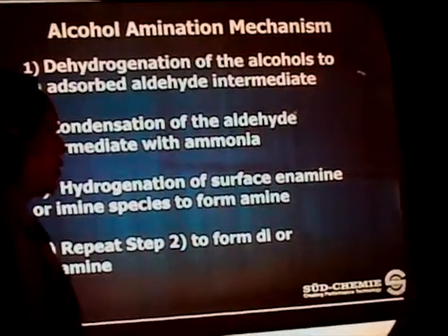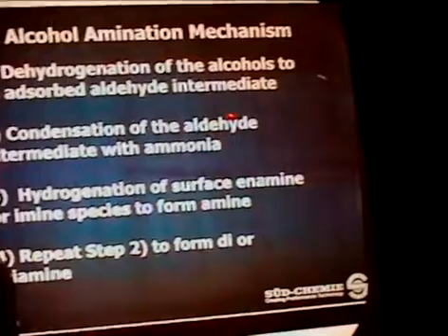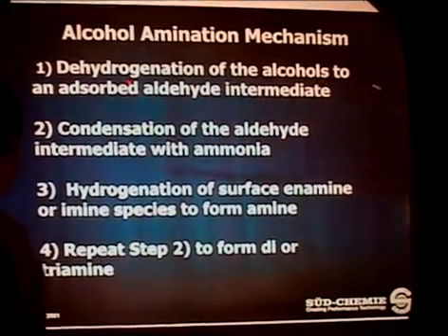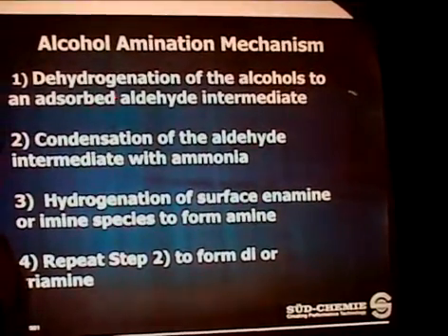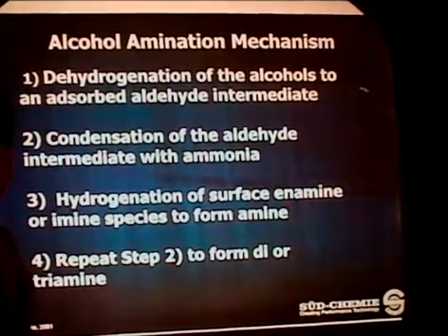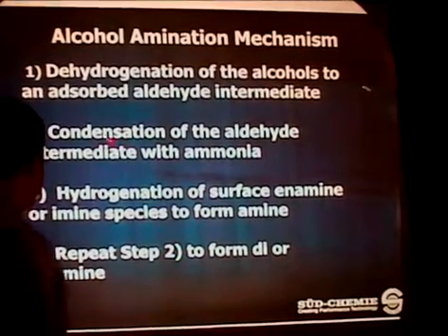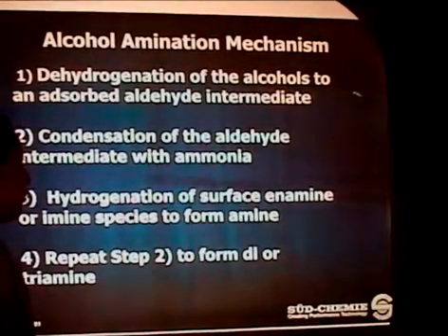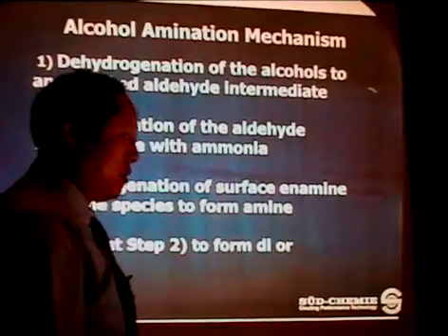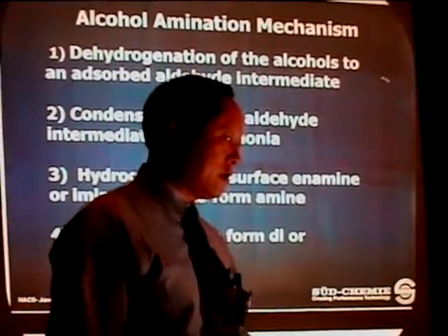First, let's briefly look at the mechanism for amination. You can immediately see that it's drastically different from a typical Fischer-Tropsch catalyst, which is polymerization. This alpha-carbon amination is well known. The first step, dehydrogenation on the surface, is the slow step. Formation of the amine species is probably pretty fast, so it maybe does not need lots of cobalt surface, and this is what we want to emphasize. Plus, this does not form a high molecular weight product, just a simple condensation of an aldehyde intermediate with ammonia. So the pore size distribution and pore requirements are probably not as stringent as for Fischer-Tropsch. Also, the cobalt dispersion does not need to be as high as for Fischer-Tropsch.